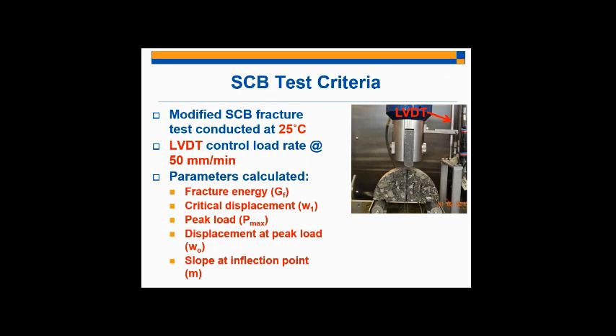And so, a little bit of discussion as to what the SCB test criteria actually is. We've taken the classic SCB fracture energy test, which is run at minus 12 degrees Celsius, and is controlled by the horizontal displacement at the bottom of the specimen. You can see the clip gauge stuck to the bottom of the specimen there. We've taken that test from minus 12 degrees Celsius, and we've run it at 25 degrees Celsius.